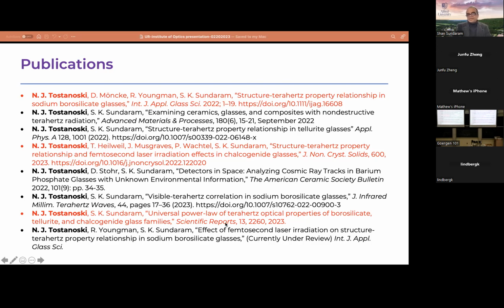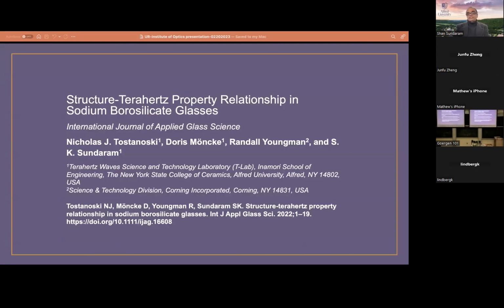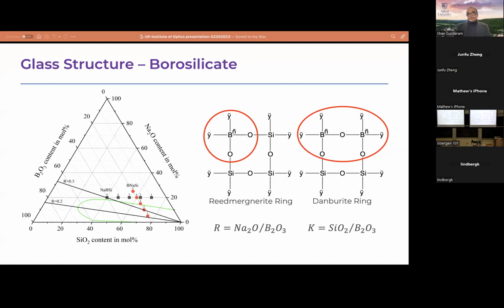And I will talk a little bit about the universal power law I mentioned at the beginning of the presentation. This is the first part of the work on sodium borosilicate, published in the International Journal of Applied Glass Science. Borosilicate is a well-known commercial composition, but for non-glass people, it's not a single composition. Whenever we say borosilicate, that's a family of glass compositions with varying mixtures of components. The 3 major components in borosilicate glasses are SiO2 silica, B2O3 boric oxide, and Na2O sodium oxide.